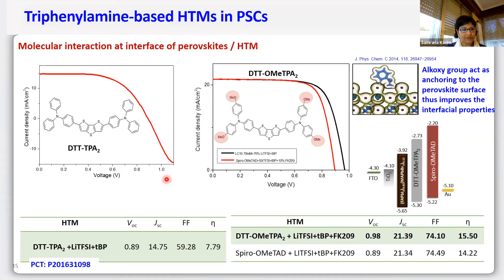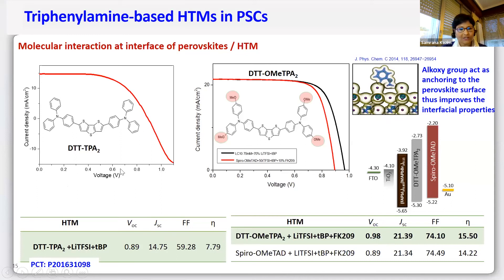Following this work, we developed triphenylamine-based HTMs, exploring how molecular interaction at the interface plays an important role. We developed terthiophene and triphenylamine-based molecules. Initially the efficiency was around 8 percent, but after molecular tailoring by adding methoxy groups, efficiency reached up to 15 percent. From this we learned that by playing with side groups — adding methoxy or alkoxy groups — we can not only tune energy levels but also improve the interfacial properties between perovskite and the HTM layer.